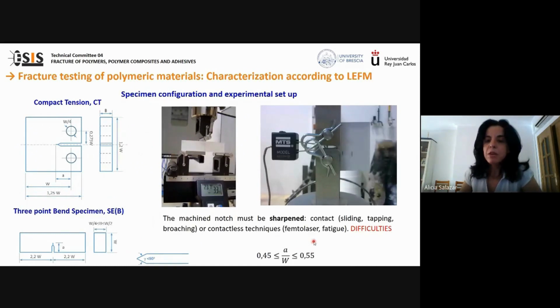The recommended specimen configurations are compact tension and 3-point bend geometries. The reason is that they require smaller sizes to achieve plane strain conditions, very important, than other configurations. Normally, the material is supplied in the form of sheet, and the specimen thickness should be identical with the sheet thickness. The width, W, is normally twice the thickness, B, but in some cases, the width can range between 2 and 4 times the thickness in the 3-point bend specimens. The two right photos show the experimental setup for the 3-point bend and the compact tension configuration.